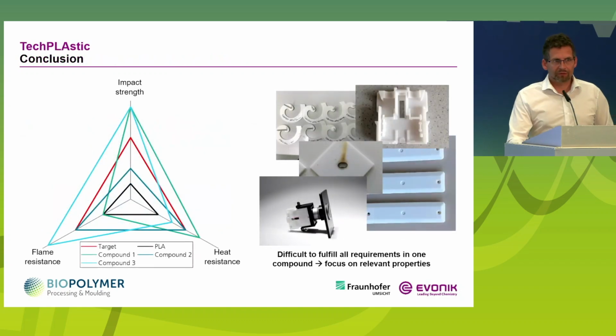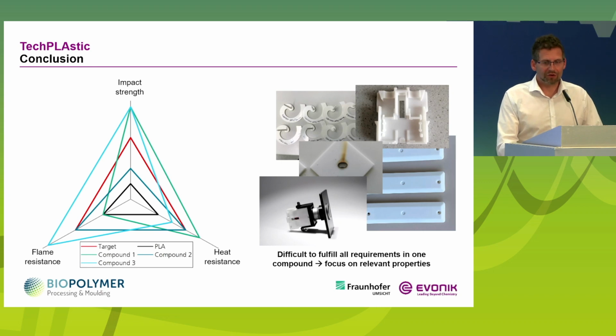Yeah, at the end, we have to state that it's difficult to reach all these three values in one recipe. So if we start with a PLA in the middle, we try to reach with the first compound all three properties, but we see that we did not reach the flame resistance good enough, and then we optimized step by step. But it was not really possible, when we now have a look at this red target triangle, to reach all properties in the same way. So we need to focus on the needed properties.